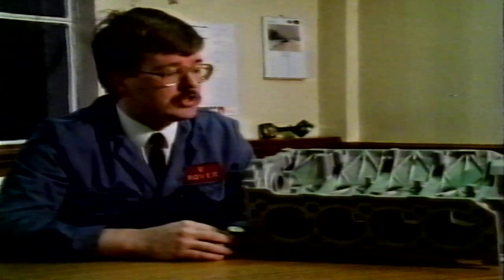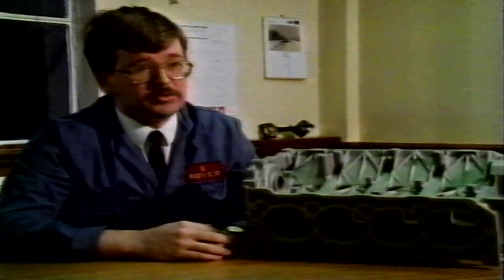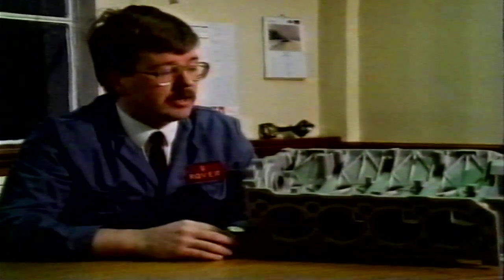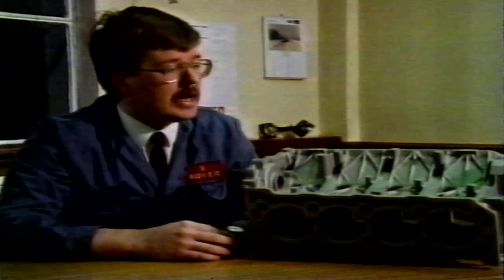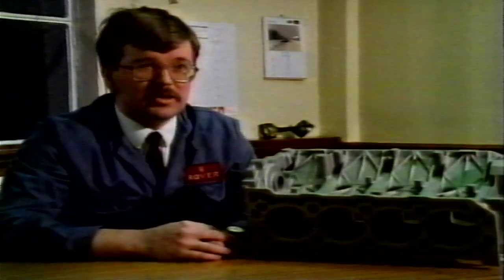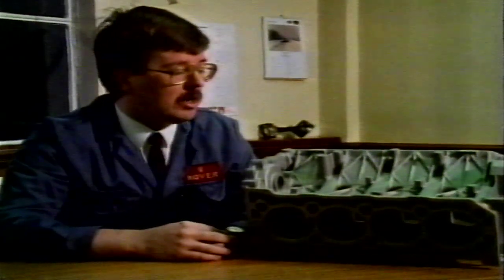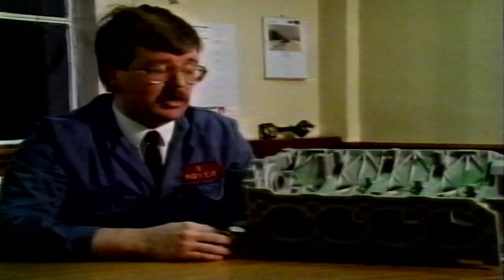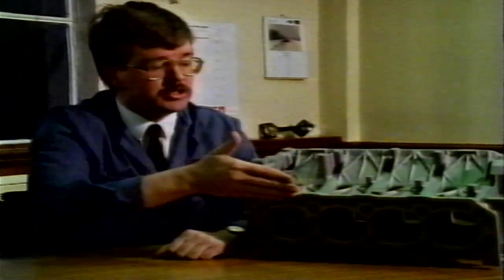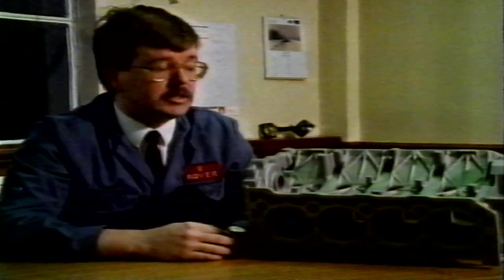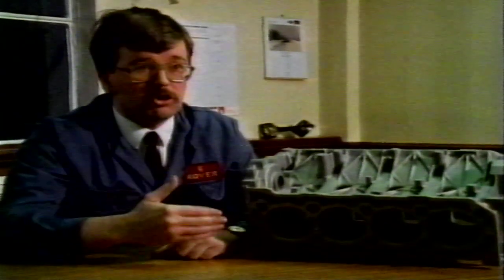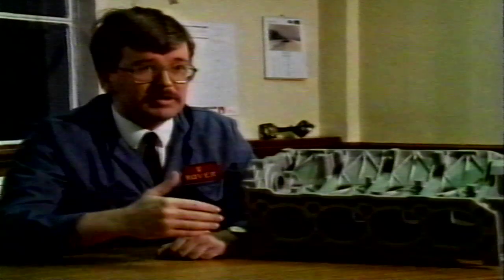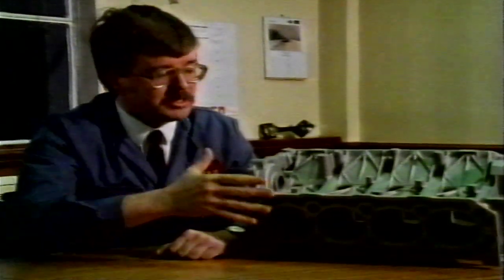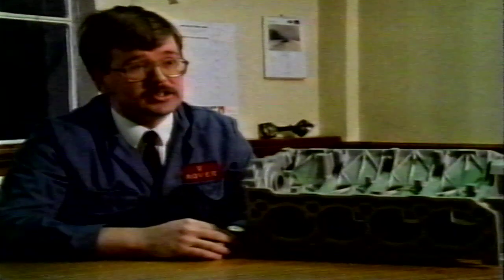The casting process we use is fairly straightforward in terms of the moulding methods we use. We produce a cavity in a block of sand, a hard block of sand, through the use of cold box core manufacture and assembly methods. Where we perhaps deviate from most other casting methods is that we apply an electromagnetic force to a molten stream of aluminium, which is then used to displace that metal into the cast mould from its base to its top under very controlled and very reproducible conditions. And that's important in terms of controlling turbulence and controlling the heat and fluid flow distribution through the casting to allow us to optimize the design against the constraints of using aluminium.